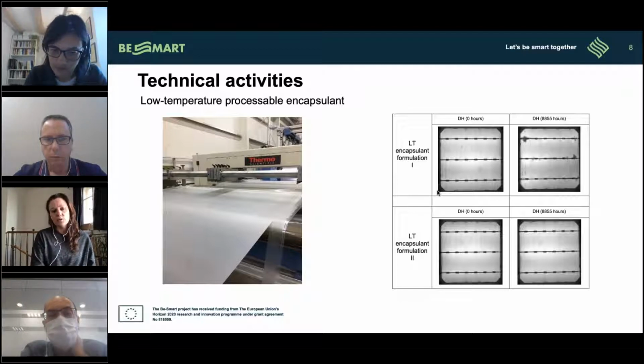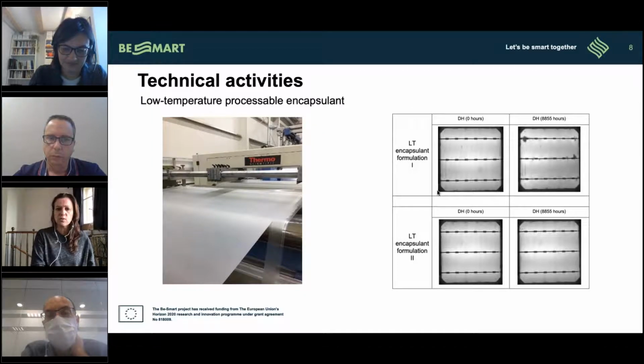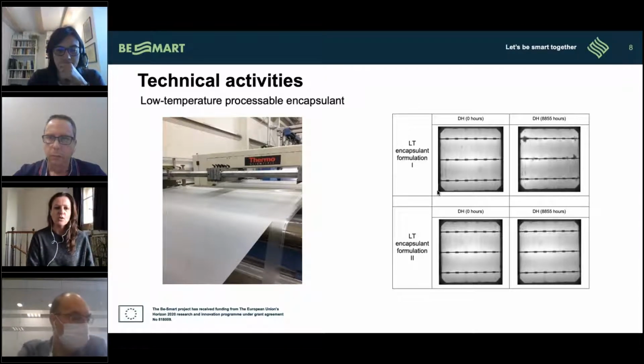I told you also about how we can decrease costs at the manufacturing level. And here our focus is on the formulation of polymers that can be processed at a lower temperature. When I say lower temperature, it is between 85 and 120 degrees, which is quite different from the usual 160 degrees of other polymers that are processed in the PV industry. Being able to lower this temperature has, of course, an impact on the cost of the lamination process, and especially the energy used for this process.